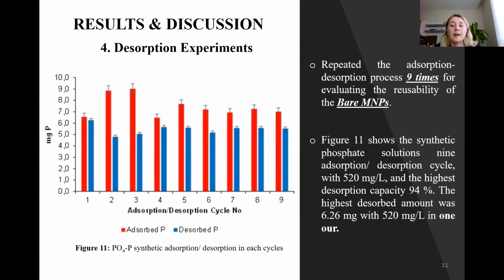However, the highest recovery at the end of the desorption experiments was 94%. The highest desorbed amount was 6.26 milligram with 520 milligram per liter in 1 hour.